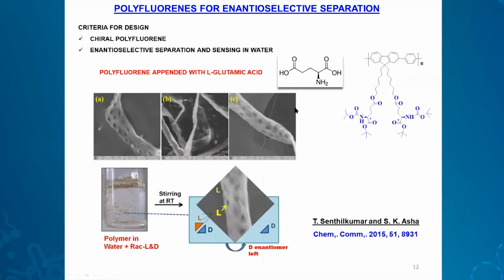So we have designed a polyfluorene molecule with this protected amino acid. This is L-glutamic acid, in the protected form here. It is appended to the side chain of the polyfluorene, making the polyfluorene also chiral. Although we have not shown it here, the circular dichroism spectra of the polymer powder confirm the chiral nature of the polymer with an alpha helix structure. And the morphology of the polymer, when scanned with scanning electron microscopy, showed these porous helical structures, porous fibrous filaments.